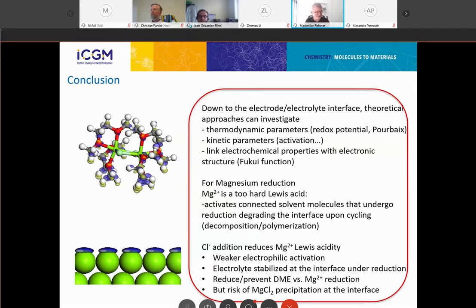Like, did somebody observe the ethylene that you propose? For ethylene carbonates, there are some experimental observations of really thick layers that were analyzed mostly to be organic. So some kind of ethylene carbonate polymer is coherent with what was observed. And it's certainly really the polymerization of ethylene carbonate with magnesium, which doesn't occur with lithium, that is one of the problems of all the solvents that have ring carbonates. And for the DME, there are some observations of ethylene production upon cycling. Of course, the problem with the interface is that it's very difficult to really observe things that are happening mostly 1 nanometer away from your electrodes.